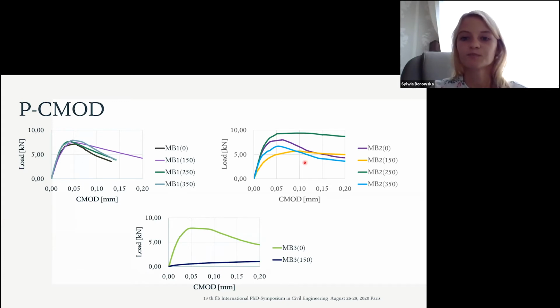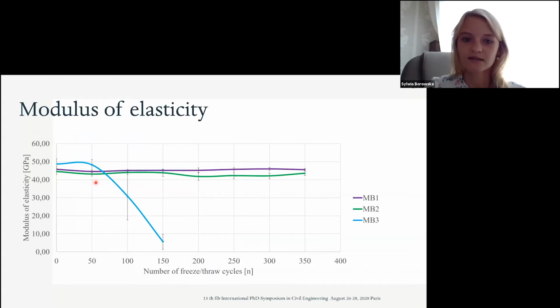in these figures. After 350 cycles, no significant effect of freeze-thaw was observed on high-strength concrete without fibers. These concretes are characterized by a larger range of elastic deformation, as shown in Figure 1, and at the same time lower resistance to fracture. Due to the more homogeneous structures and fewer voids, MB1 series concrete didn't degrade as a result of freeze-thaw cycling after 350 cycles.